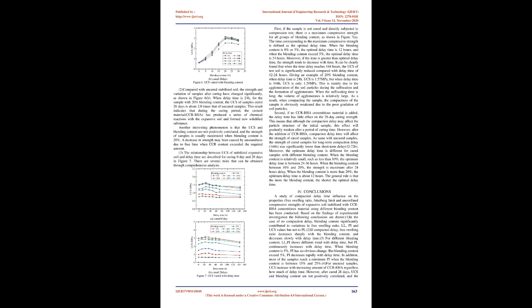As a result, for different blending content, PI shows different trends with delay time. For pure expansive soil sample, PI increases with delay time. When blending content is 5%, PI has very weak change. But when blending content exceeds 5%, PI decreases obviously with delay time. The above phenomenon mainly comes from two aspects. On the one hand, with increase in CCR-RHA content, due to depletion in the double layer, the soil particles come close to each other and get flocculated. These flocculated structures entrap some amount of water in the voids, which causes an increase in plasticity characteristics.